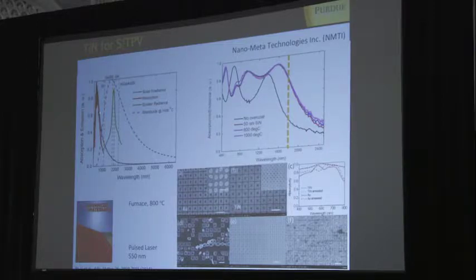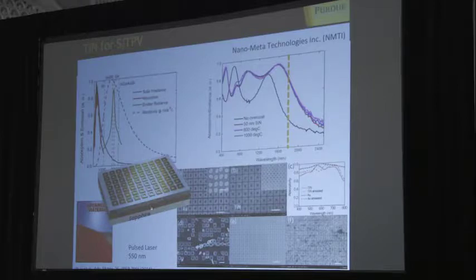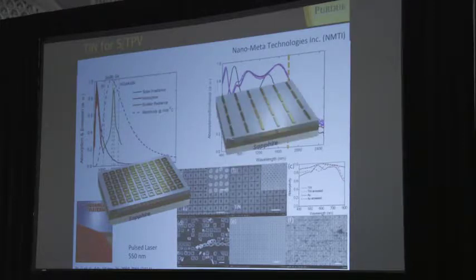So you could see that the absorption matches very well the sun spectrum, this red curve and black one. In addition, you could design an emitter just on the other side of your object, which you heat up to high temperature. And the emitter, this is our absorber, could be just simple, these rods of titanium nitride. What could be simpler? As opposed to another approach based on photonic crystal, which is a very difficult and complex way, and it's hard to actually preserve structures at high temperatures.